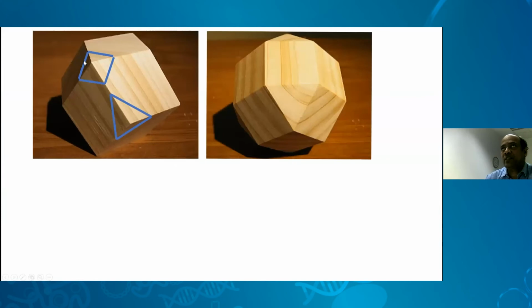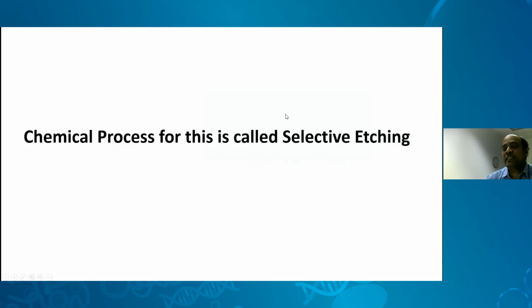So now we would like to change to a different facet. One way is a simple etching process, or cutting process, which just cuts down these edges. If we cut down these edges, then the triangle facets come. Here is a square type of facet, and finally we get this structure. If all the vertices or corners have been cut down, then we have to turn out this facet. And this is what is called selective etching.